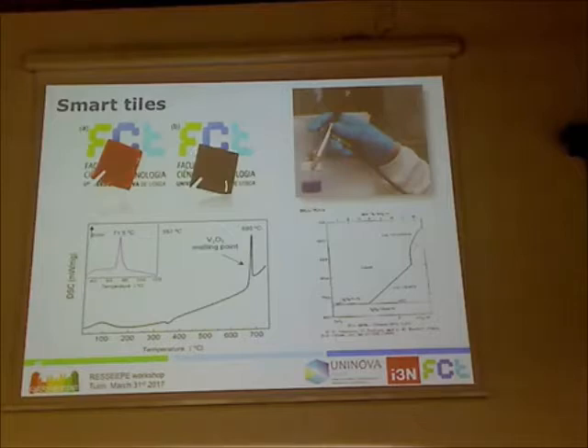How do we solve this problem, at least partially? If you do a thermal analysis of V2O5 in this case, you see it has a melting point around 700 degrees. If you look at the phase diagram, you see it melts around this temperature.